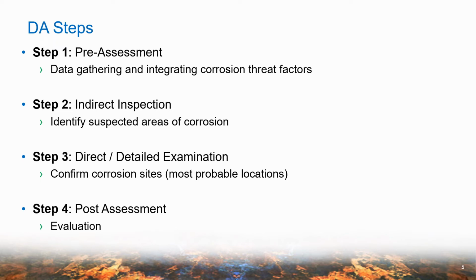If it is for external corrosion direct assessment or stress corrosion cracking direct assessment, you are trying to confirm, can I physically work on the pipeline? Are there conditions that can prohibit the completion of the indirect inspection and completing the digs, which is the direct examination stage? For instance, if you cannot work on the pipeline to capture pipe-to-soil, coating survey data, depth of cover, and soil resistivity, if you cannot physically access the pipeline to conduct the inspection, ECDA is not practical. So you have to complete the feasibility assessment, confirm it's going to be feasible, select your indirect inspection tools, and then select your regions.